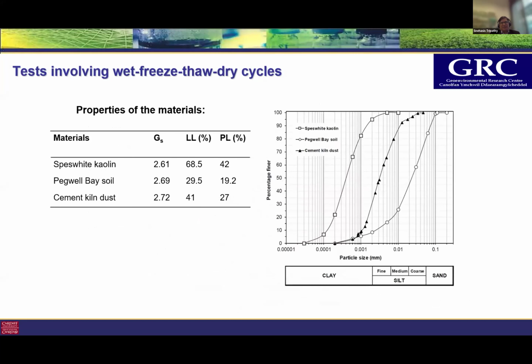Three materials I'm trying to show here. One is Speswhite kaolin, which is a clay, Pegwell Bay soil, which is a frost-susceptible soil from England, and here we've got a cement kiln dust, which was brought from a local cement company. You can see the liquid limits here. Speswhite kaolin and cement kiln dust, you can see the grain size distribution here. They can be considered to be very fine material, whereas the Pegwell Bay soil grain size distribution here contains a little bit of sand as well.